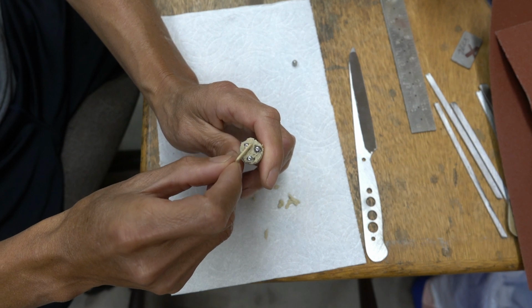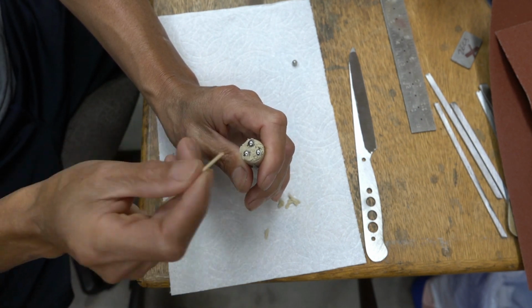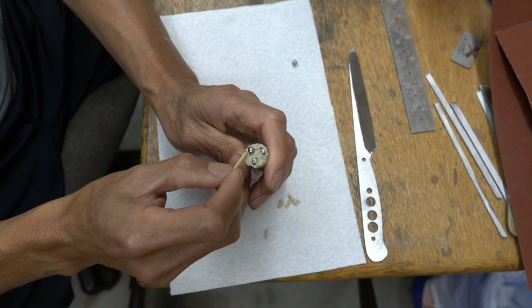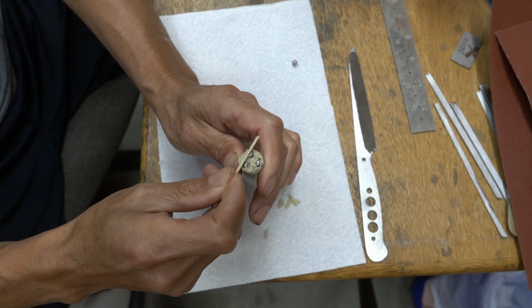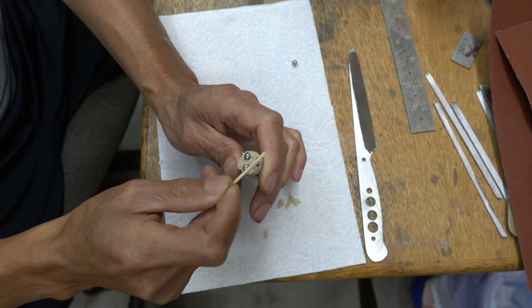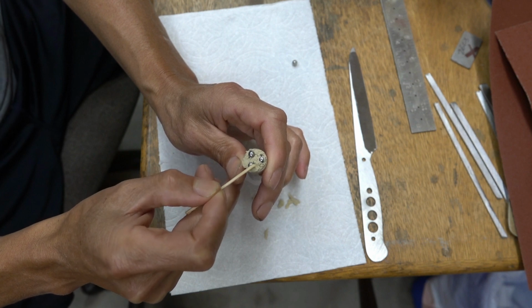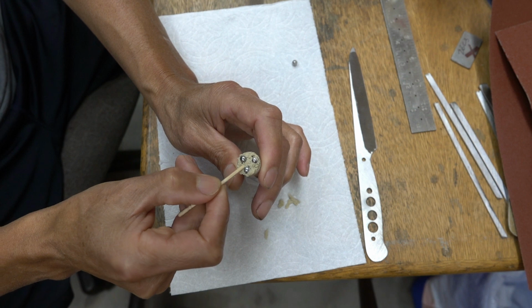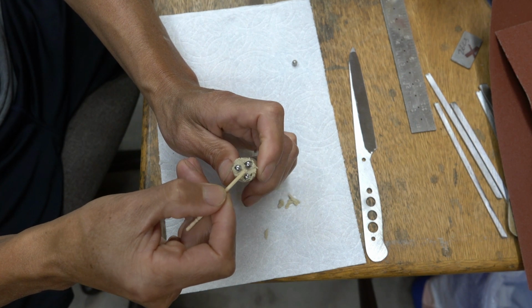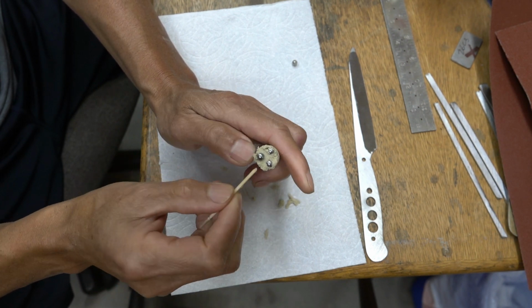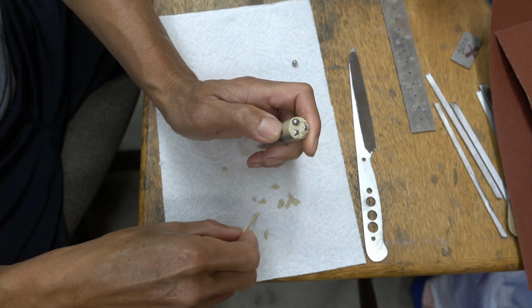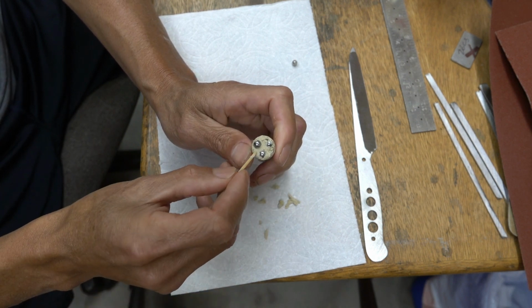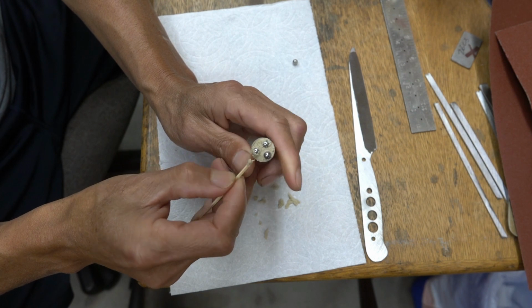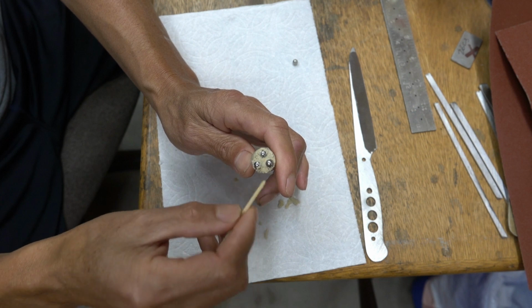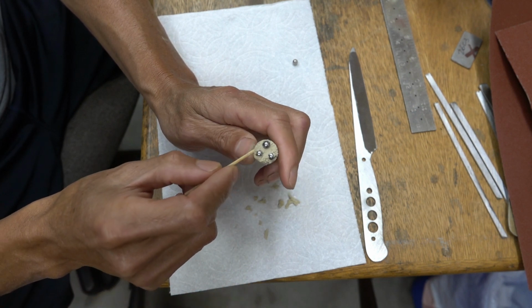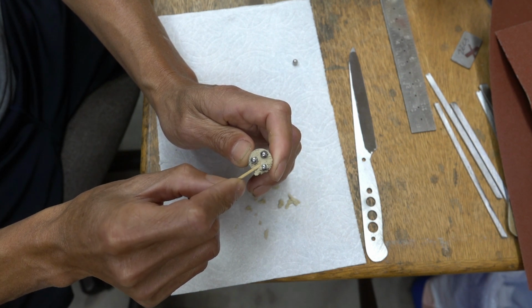Right. So now let's do some more. Now, when the matrix is strong, the fixed abrasive is going to be right on top of the carbide, so it won't do anything pretty much because the carbide is much harder than the abrasive, so it's not going to do any cutting. The loose abrasive actually continues to go between the carbide. To demonstrate the point, you can think of it as common sense, because that's what will happen. But when there's enough exposure, you can have an analogy of teeth in the gum. How strong your gum is determines how well it holds on to highly exposed teeth, or in this case, the matrix that got undercut that much.